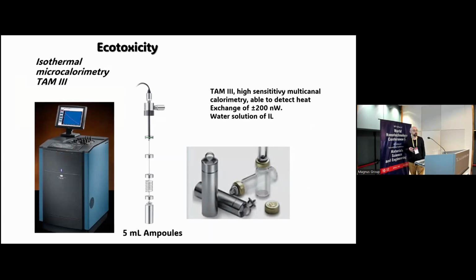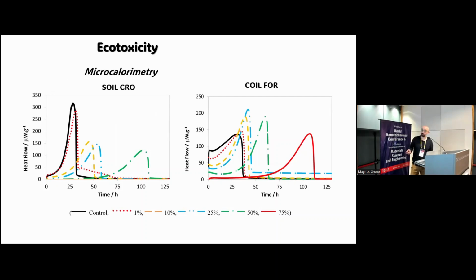We have also measured, as I told, ecotoxicity of our compounds in the pure liquid state. In this case, we are presenting an isothermal calorimetry that is able to detect 200 nanowatts of change in our system. We are using soil samples, and we can understand how the heat is released by microorganisms in the soil when we add the ionic liquid. You can see here in black the control without ionic liquid, and the other ones are with ionic liquid. When we add ionic liquids, there is a shift to different, higher times. Maybe the microorganisms are stabilizing in this new system.